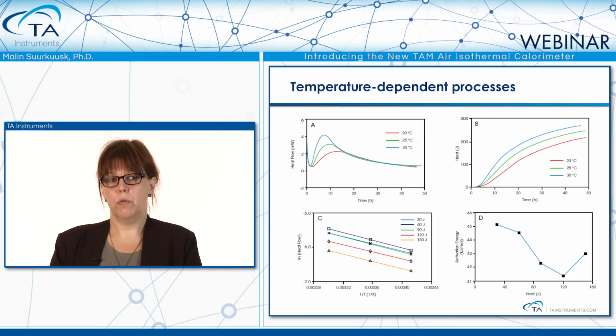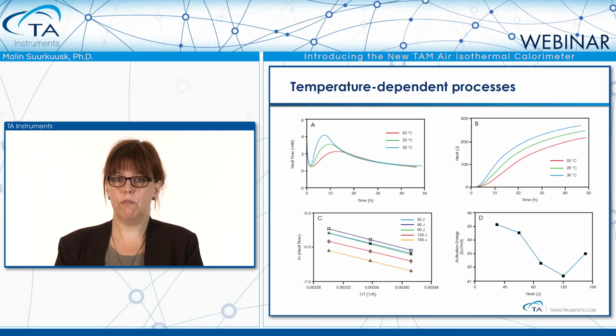So at different extent of the reaction, you will have different heat rates. And heat rate, I mean it's the heat flow we are measuring, which is directly related to the rate of reaction. So in an Arrhenius relationship, you can directly plot the heat flow you are measuring in a logarithmic form. And you plot that versus the inverse of the absolute temperature. And we can see that we get a lot of different activation energies out of this, and those are plotted in the lower right curve, the D curve. So we can see there are a lot of processes going on at the same time or after each other in the cement hydration process.